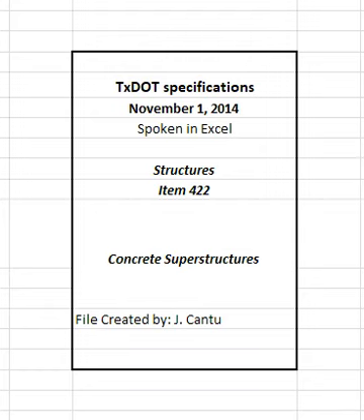the slab being placed. Use construction joints, when required for slab placements on steel beams or girders, as shown on the plans. Ensure the previously placed concrete attains a compressive strength of 3000 psi when staged placement of a slab is required on the plans before placing the next stage concrete. Multiple stages may be placed in a single day if approved. Use an approved placing sequence that will not overstress any of the supporting members where plans permit staged placing without specifying a particular order of placement.